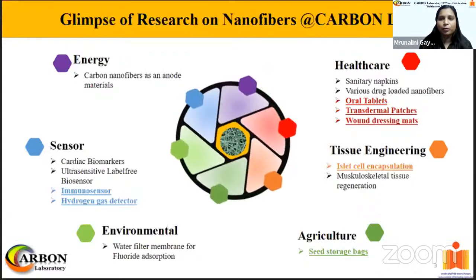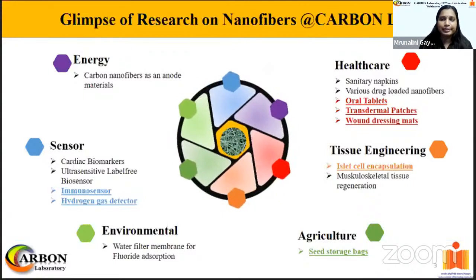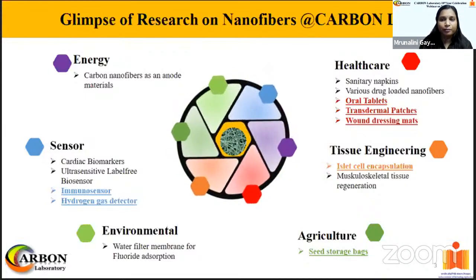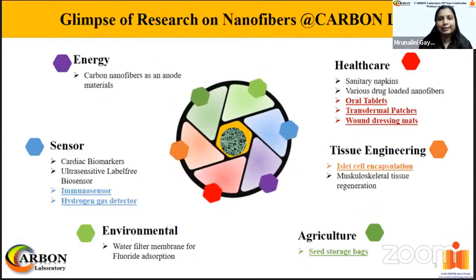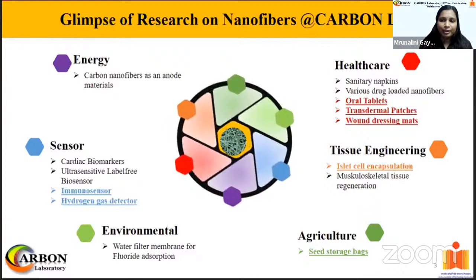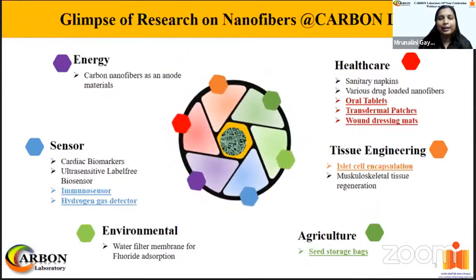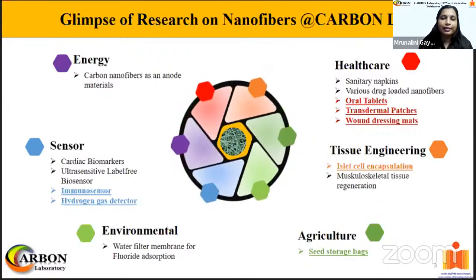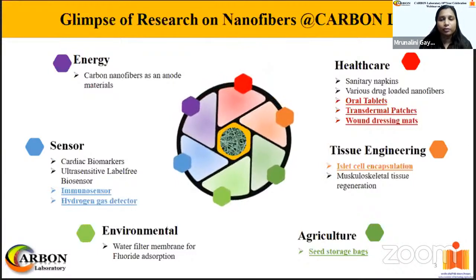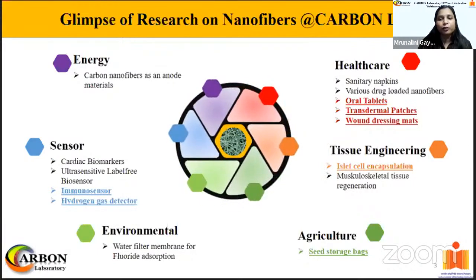In Carbon Lab, we have explored the applicability of electrospun nanofibers in various sectors. In healthcare, we introduced nanofibers for feminine hygiene and as drug excipients. Considering the cell adhesive mechanism, we fabricated aligned and patterned nanofibers for bone regeneration and further islet cell encapsulation for diabetic cure. In agriculture, for the first time, we introduced seed storage bags of nanofibers. Then, amine functionalized nanofibers for fluoride adsorption in polluted water for environmental remediation. In sensors, we developed highly porous as well as hierarchical micro nanostructures as biosensors and gas sensors. And in the energy field, we explored carbon nanofibers as an anode material. Today, I shall discuss some of the notable contributions from our lab.